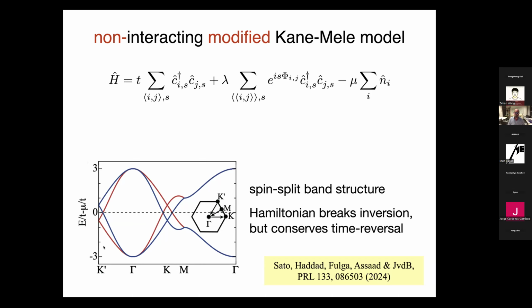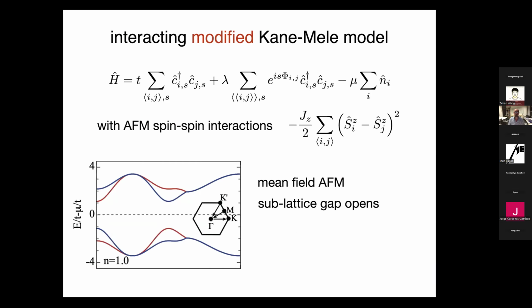And here's the band structure. There's the gamma point. You see that the bands are spin degenerate at K prime and K, where the Dirac cones are in graphene. And now we have a spin splitting of the bands. K prime and K actually have opposite splittings of the bands. Okay, so we have a spin split band structure. The Hamiltonian breaks inversion, but conserves time reversal symmetry.